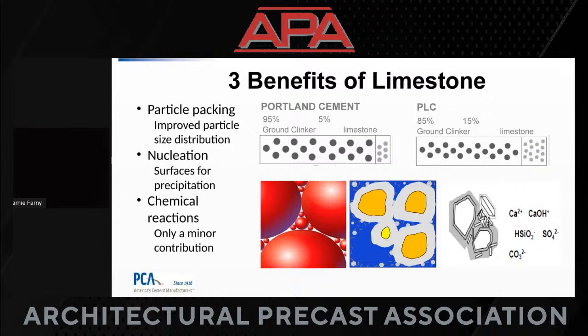And because limestone is just a little softer than clinker, when we grind them together, the fines typically are produced more from the limestone portion. So these smaller particles are filling in between cement particles, which are themselves pretty fine already, right? But we're filling in between them. So we get this particle packing going on. That means we have a tighter matrix. Everything fits together just a little bit better. We've got an improved particle size distribution. So we don't have one size of everything. We've got this nice blend from the larger down to the very small, submicron kind of particles.